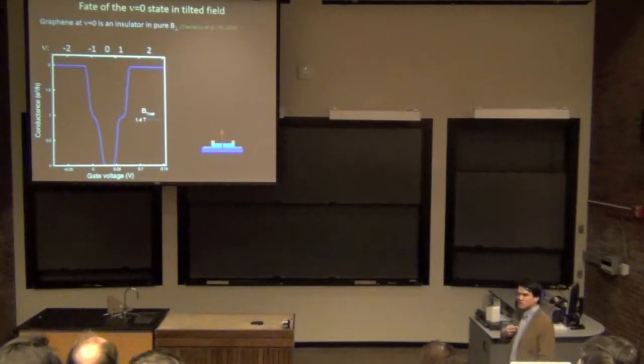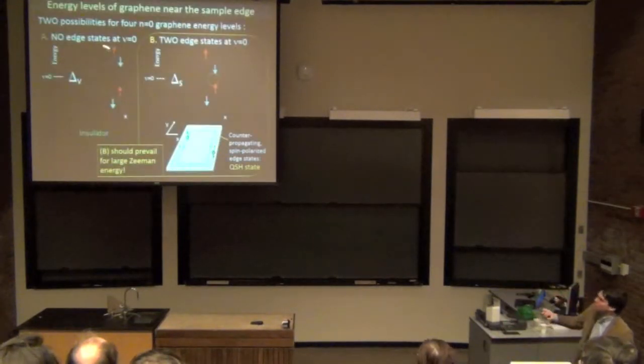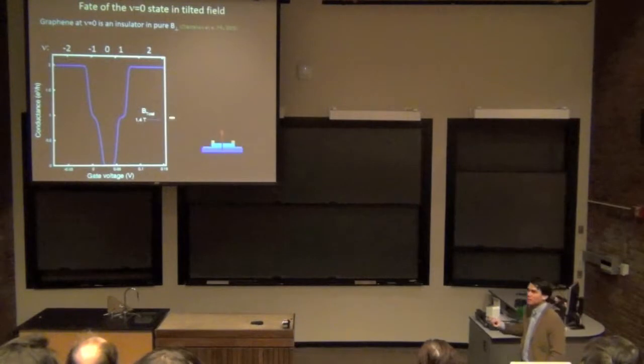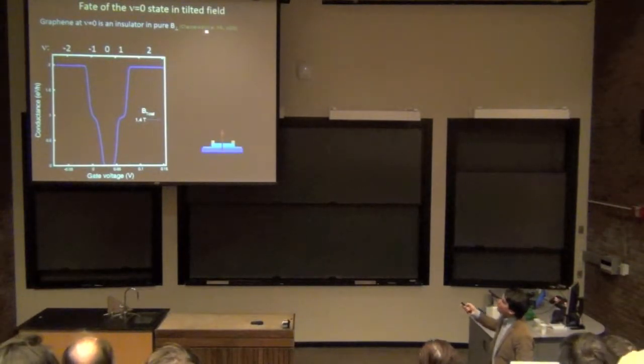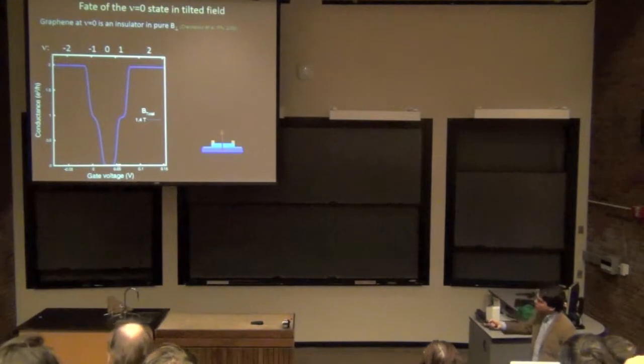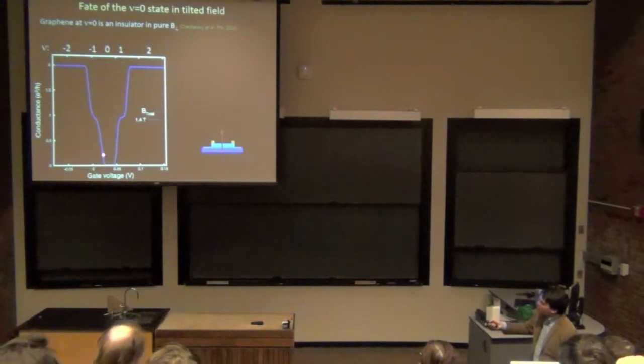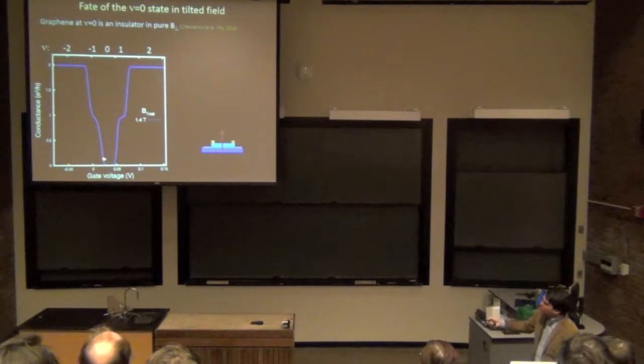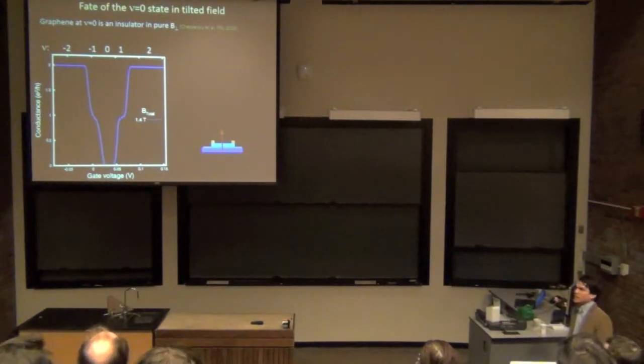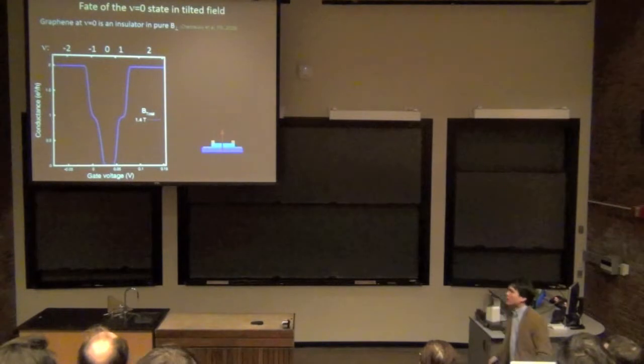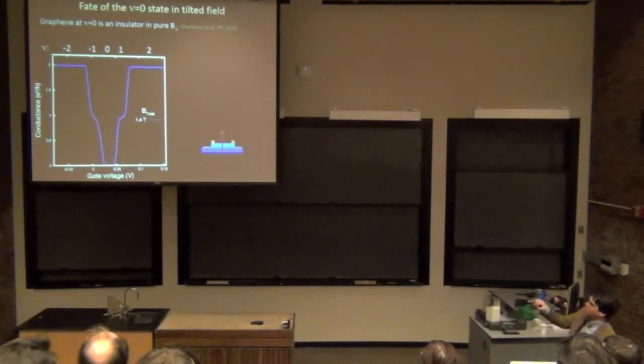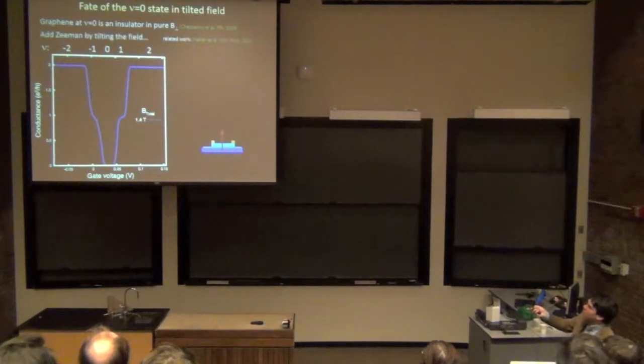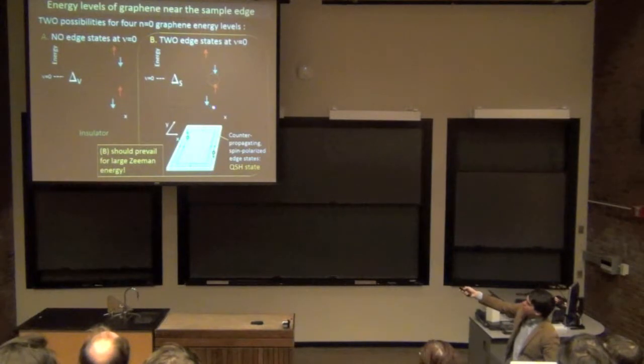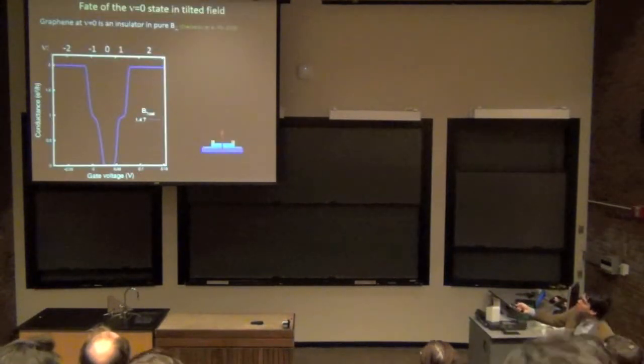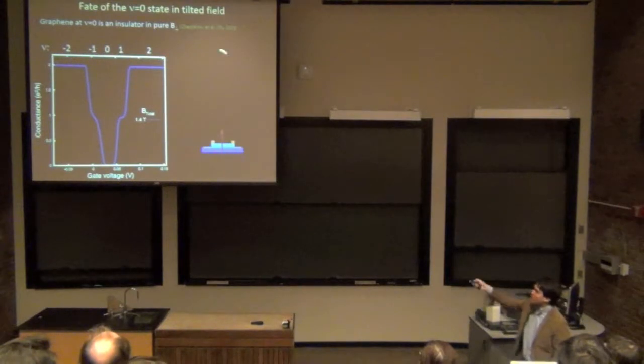So nature has given us an answer. The answer is that it's the state on the left, in perpendicular magnetic field. This was discovered back in 2008. You can see that down here, this is nu equals zero, as labeled up there. Basically, there's zero conduction there. It's an insulating state. So we were not happy with the answer that nature gave us, and so we decided to add Zeeman energy again, just playing with the spins of the system by tilting the sample and increasing the magnetic field.